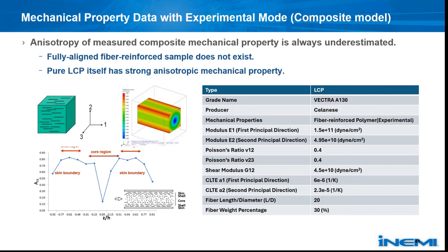So there are some methods that can calibrate this issue based on the data input by composite. And we already know that it works well for general plastic, where the polymer base is isotropic. However, the pure LCP itself has a strong anisotropy. So we need to try another method to overcome this issue. Next page.